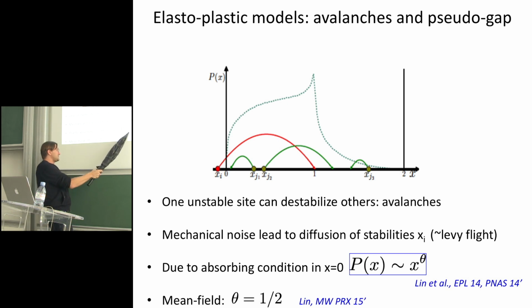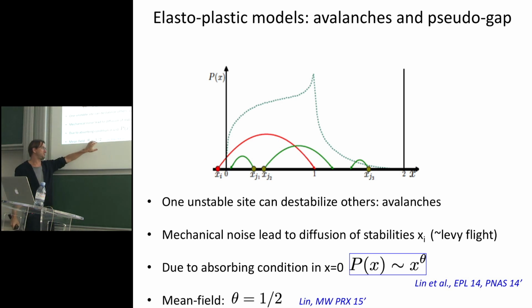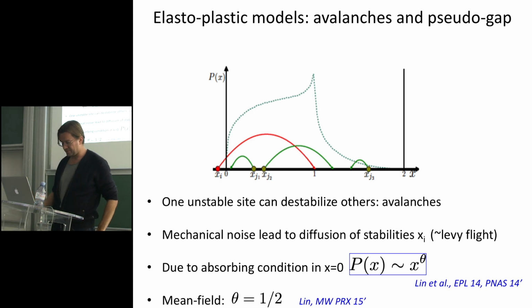Now you can work out how the distribution of concentration of a Levy flight walker acts close to a boundary, and you find that actually there is a non-trivial exponent. In mean field, if you really have Levy flights, this exponent theta is 1/2. And as you will see, it works not too badly in 2D, or as I will show you later on.